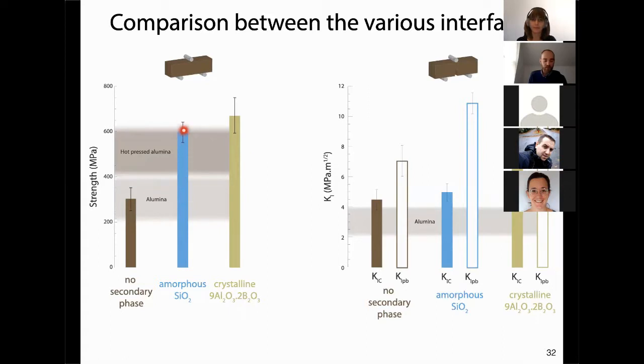And then if we start adding some interface, some glue, this mineral glue in between, we get to a strength that is now almost higher than the best alumina we know how to produce. And finally, with this crystalline phase, we see that we increase the strength a bit again.